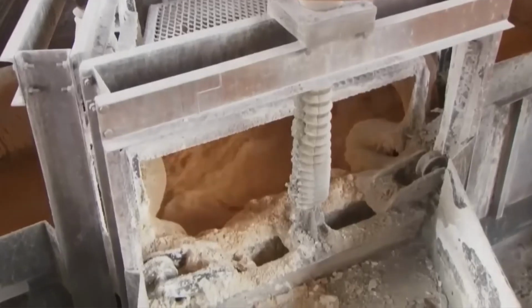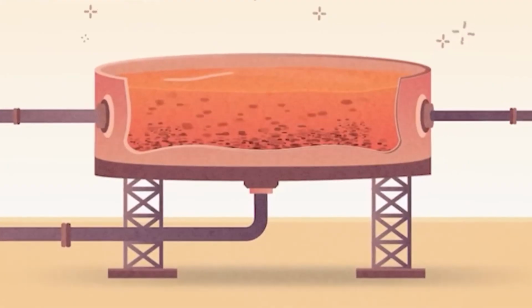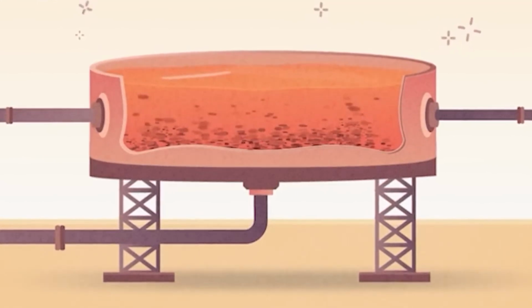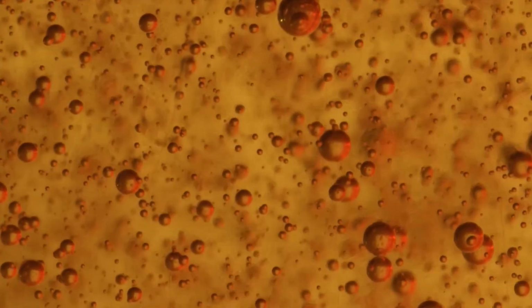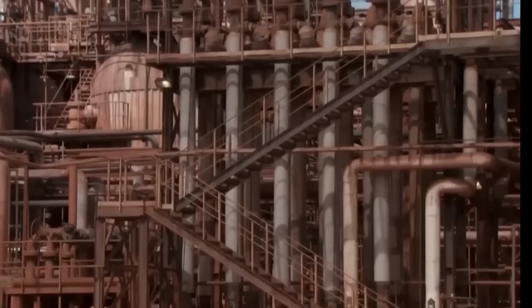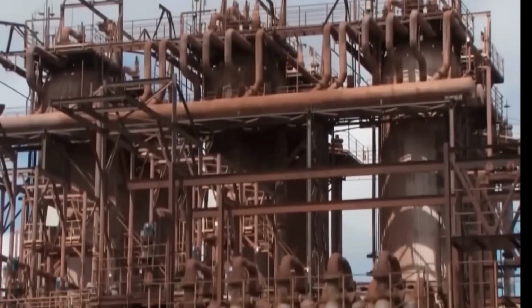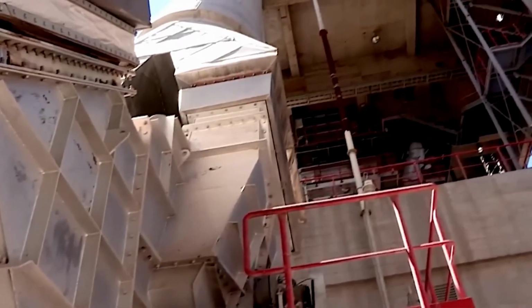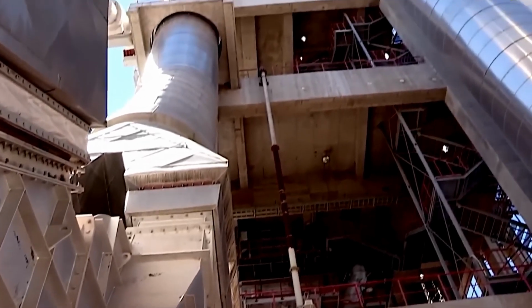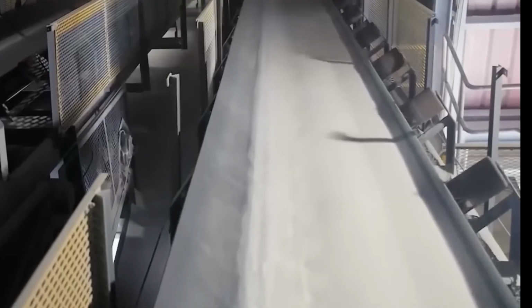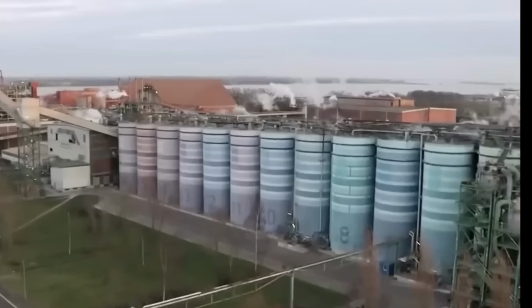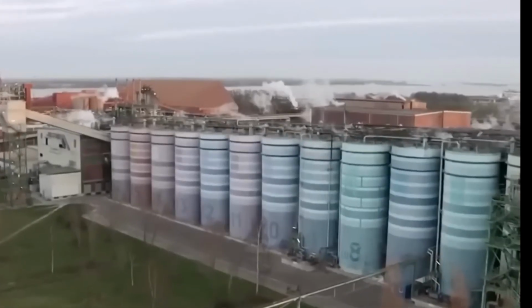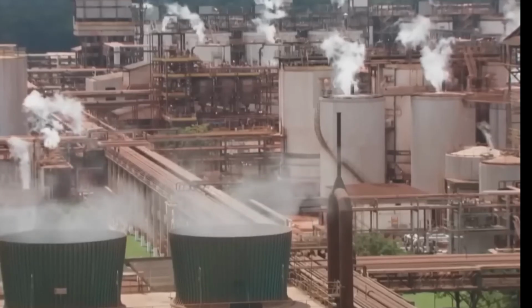Once these impurities have settled, the remaining liquid, which has a dark coffee-like appearance, is pumped through a series of cloth filters. These filters trap any remaining fine particles, ensuring a purer solution. The trapped material is then washed to recover any remaining alumina and caustic soda, which can be reused in the process. The filtered liquid is now ready for the next stage, precipitation. It is pumped into a series of towering, 6-story high precipitation tanks. Inside these tanks, seed crystals of alumina hydrate, alumina bonded to water molecules, are introduced from the top.